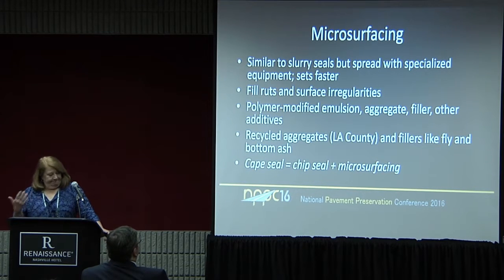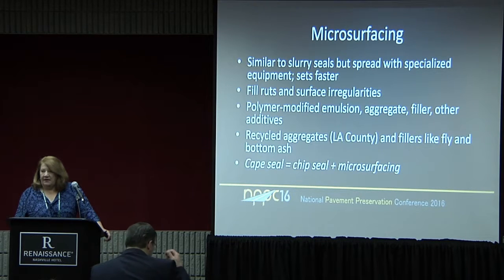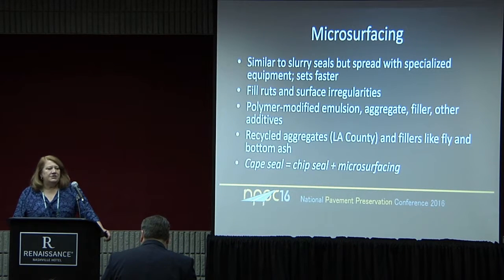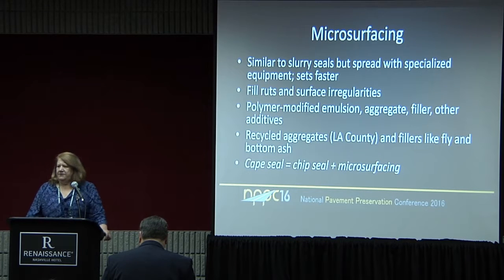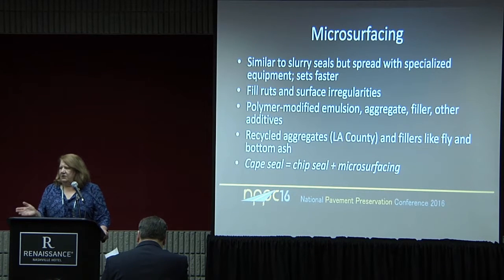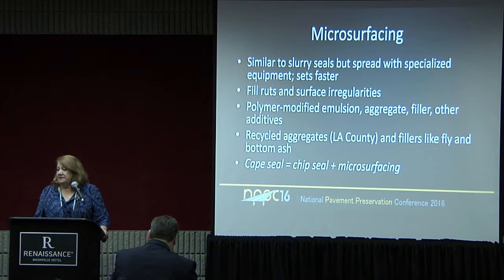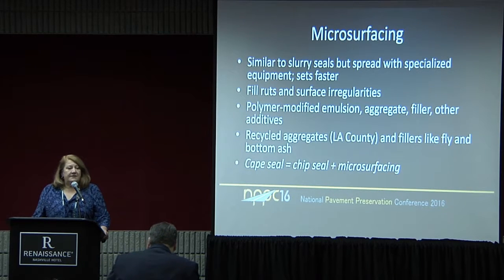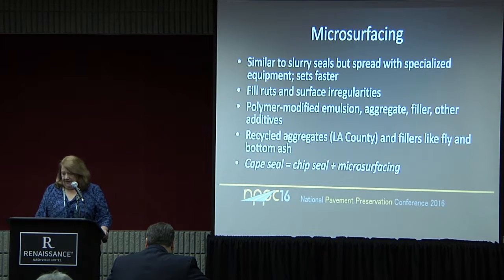So again, this is another application where you can use both recycled, reclaimed aggregates and alternative binders, including rubber. Microsurfacing, again, aggregates and binders can be recycled, sustainable materials in these types of applications. LA County, again, has experience with using recycled aggregates in these applications. And as you heard yesterday at the field demos, in that particular example, they used cement as the filler, but this is an application where you could use some of those ash materials, fly ash or bottom ash, as your filler in that application.